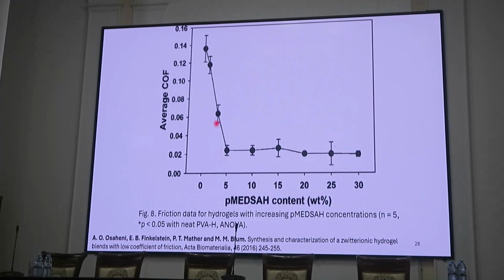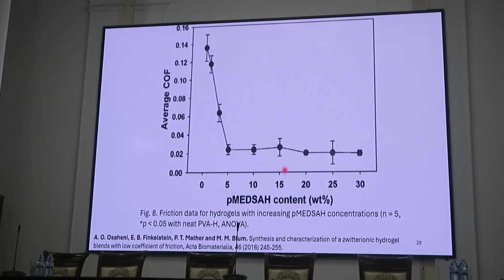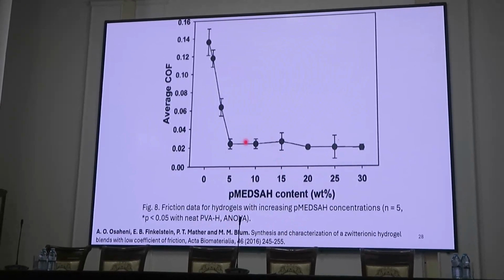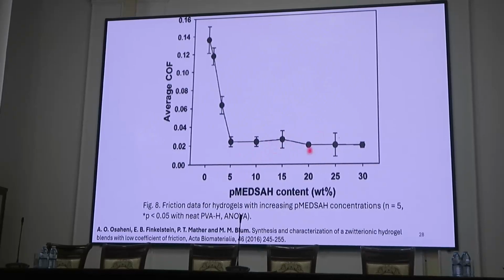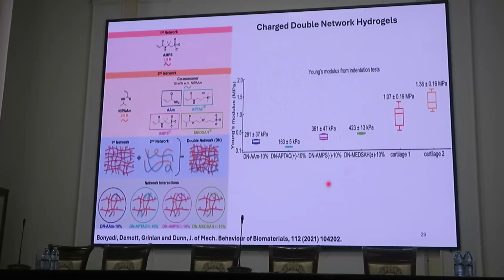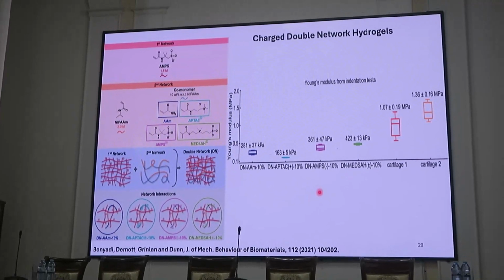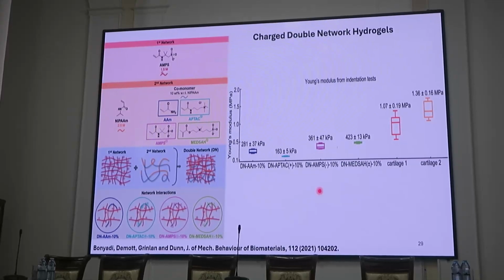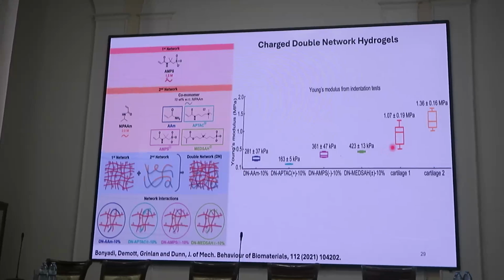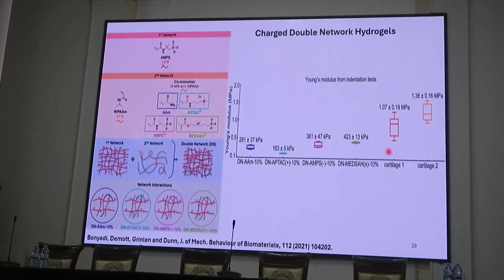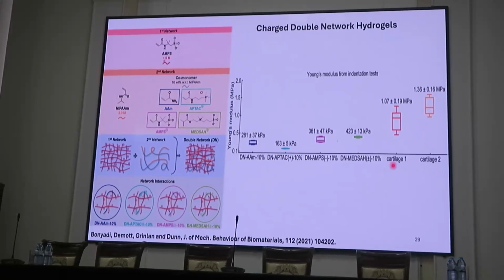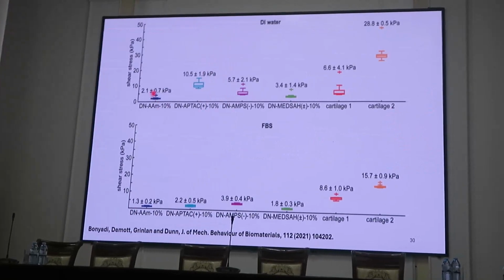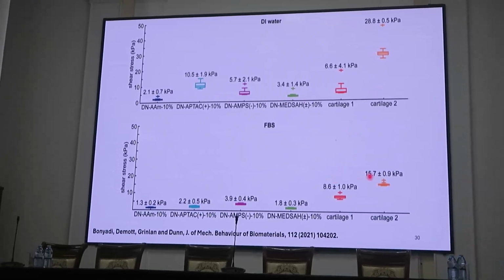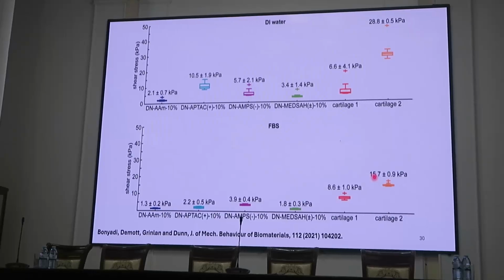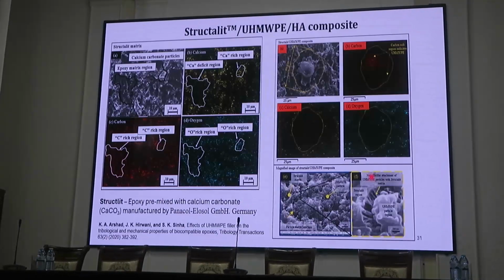And for example, the average coefficient of friction can be reduced if you increase the zwitterionic content inside another molecule, for example in PVA, and about 10% can do a very good job for this. A similar idea has been used here as well, where a zwitterionic polymer has been added to some other polymers and a hydrogel has been made. You can see that by making some composites, the mechanical strength can be close to cartilage, but not yet, and the friction property is quite good even compared to cartilage. So by doing this kind of innovation, it is possible to improve upon the artificial material for implant application.